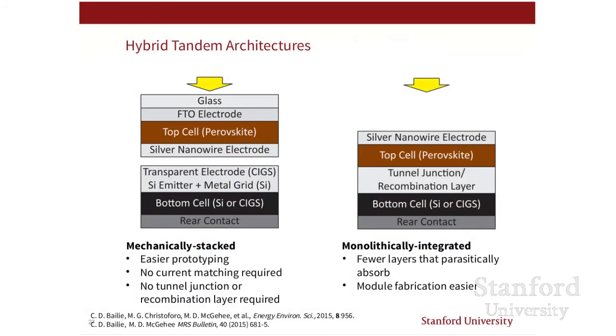On the other hand, you can make a monolithic cell where the perovskite is directly deposited onto the silicon or CIGS solar cell. If you do that, you have to match the current densities. If one of them puts out less current than the other, it will set the current for the stack. And that means you have to calculate and obtain exactly the right band gaps so that the 2 cells each get the right amount of current.